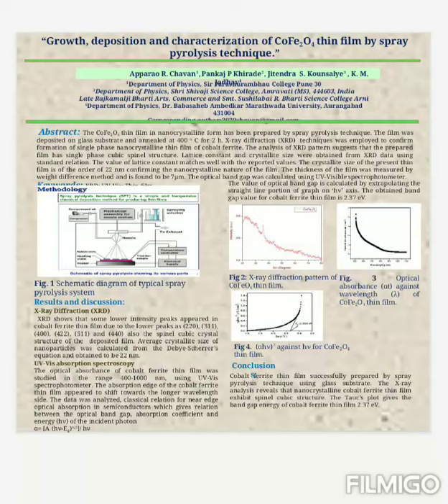The data was analyzed using the classical relation for near edge optical absorption in semiconductor, which gives the relation between optical bandgap, absorption coefficient and energy of the incident photon. The relation is alpha equals A times (h nu minus Eg) to the power n by 2, divided by h nu. This is the formula of band gap energy. The band gap was calculated by Tauc plot relations; the optical value of band gap is calculated by extrapolating the straight line portion of the graph on the h nu axis. The obtained band gap value for cobalt ferrite thin film is 2.37 electron volt.